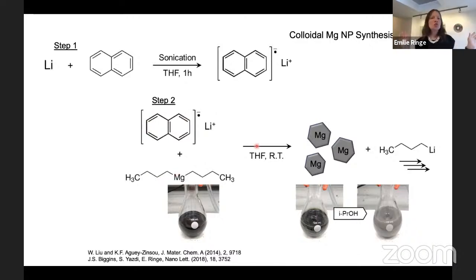And so the synthesis is relatively simple. You take lithium and naphthalene, that puts an electron on this electron carrier. This wants to get rid of its electron, and it's mixed with a magnesium organometallic precursor in THF under argon atmosphere. A little bit of time, room temperature, get beautiful metallic magnesium nanoparticles, then quench that with isopropanol, and get very nice crystalline particles.